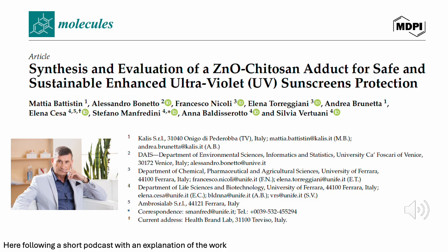Okay. And just as a quick reminder for the listeners, SPF, that's the sun protection factor, tells you how well a sunscreen protects against UVB rays, the ones that cause sunburn. Right. And UVA-PF, that's the UVA protection factor, which indicates protection against UVA rays, the ones that penetrate deeper into the skin and contribute to aging and skin cancer. Exactly. And what they found is that the sunscreen with ZnO@CS had both a higher SPF and a higher UVA-PF compared to the sunscreen with just plain zinc oxide. Excellent. The differences were statistically significant, which means it wasn't just random chance.